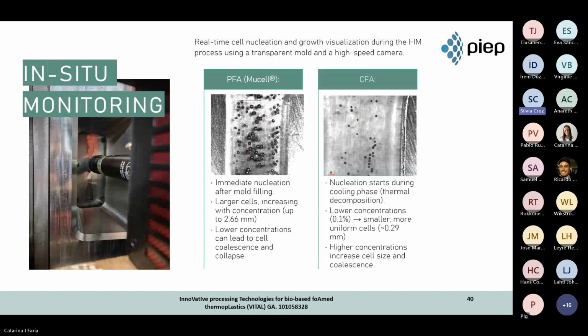And on the next slide, here we can see an example of in situ monitorization of the foam injection molding process, which allows real-time observation of cell nucleation and growth inside the mold. Although this methodology was initially applied to conventional polymers, it became extremely relevant when we aimed to transfer the process to bio-based materials, which have different rheological behavior, crystallization rates, and thermal stability.